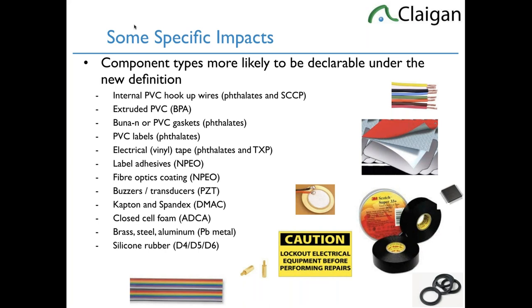The other one, which is quite surprising, is in silicone rubber. It's the building block. Silicone rubber is usually made from cyclosiloxane monomers, particularly D6 cyclosiloxane. And if you actually look at the safety data sheet from the unmolded silicone fluid, the cyclosiloxanes will be well above the 0.1% declarable level. But after it's polymerized, it often drops below. But usually the D6 is still around 700 to 900 ppm. Be amazed how common the D6 cyclosiloxane is in silicone rubber. It's the building block, and it remains residual very close to the 1,000 ppm declarable limit, and sometimes goes above.